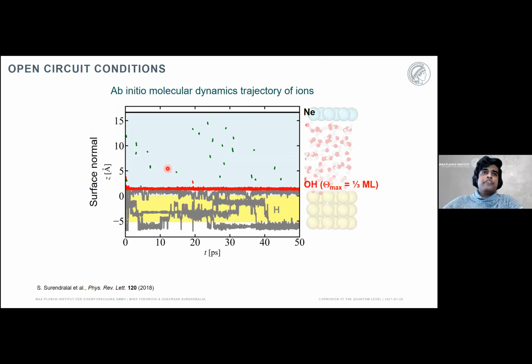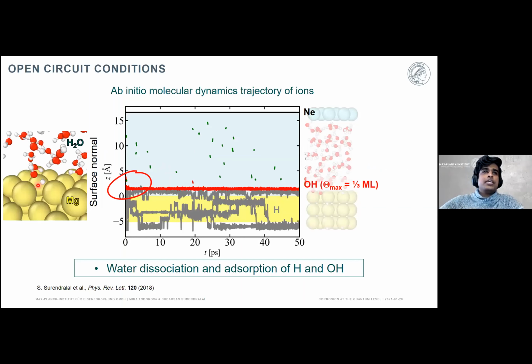So what happens very quickly is that you see a water dissociation reaction on the surface of the magnesium. The presence of the OH that is adsorbed on the surface is indicated by the red line over here, and the hydrogen that is adsorbed on the surface is much more mobile, as you can see in the movie, and it's able to occupy surface as well as subsurface sites in the magnesium. This is what you observe under open circuit conditions where you don't apply any sort of field.